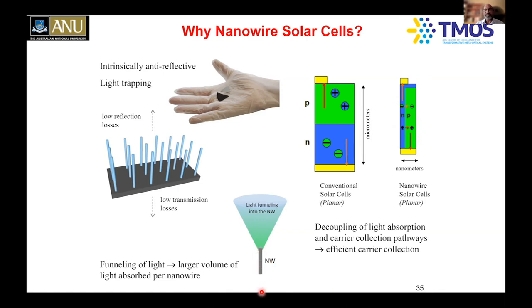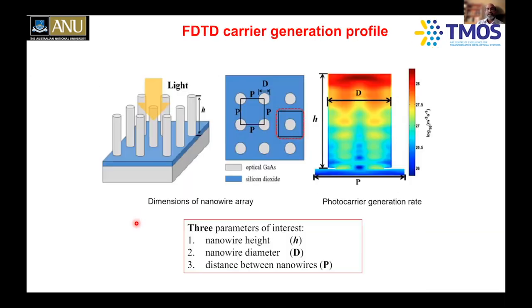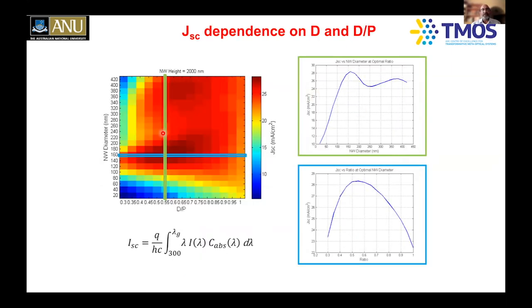Also, due to the high refractive index of the nanowire, they act like light funnels. They also have low reflection properties, which means you don't have to put on any anti-reflection coatings or anything like that. Again, we've done a lot of simulations to look at what should be the height of the nanowire, the diameter of the nanowire, and the distance between the nanowires. You can see that most of the current is generated at the tip of the nanowire, indicating that you don't need very long nanowires. Typically a nanowire about 2 or 3 microns long is more than sufficient if you're using gallium arsenide or indium phosphide, for example. And we also found that the nanowire diameter should be around 150 to 160 nanometers.